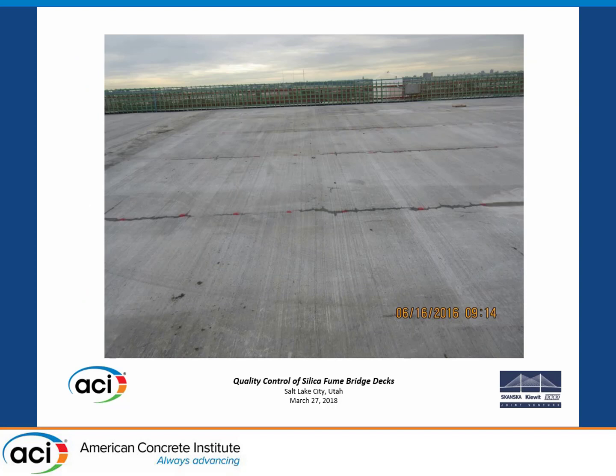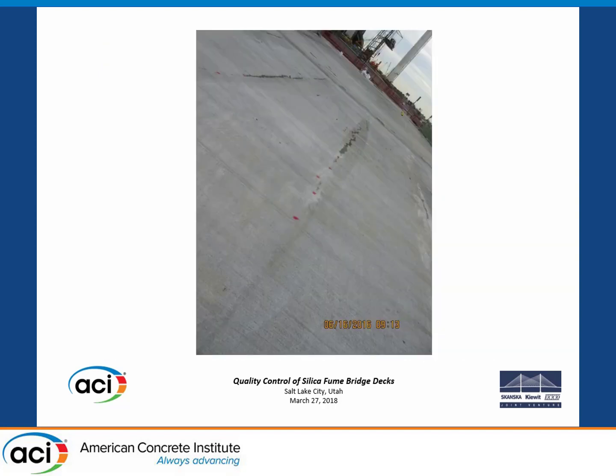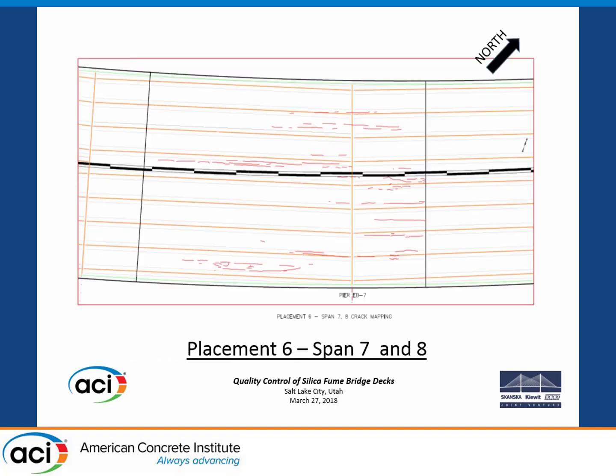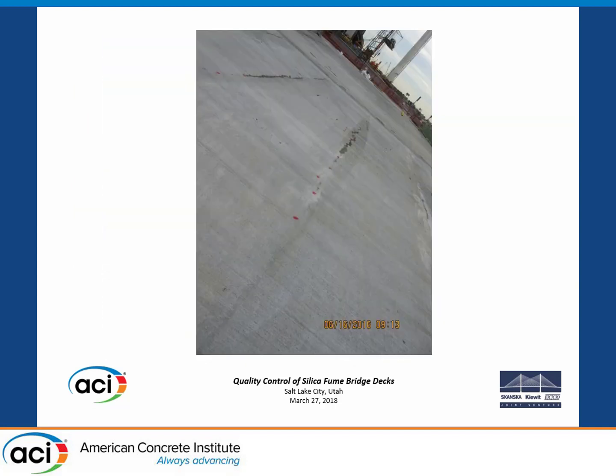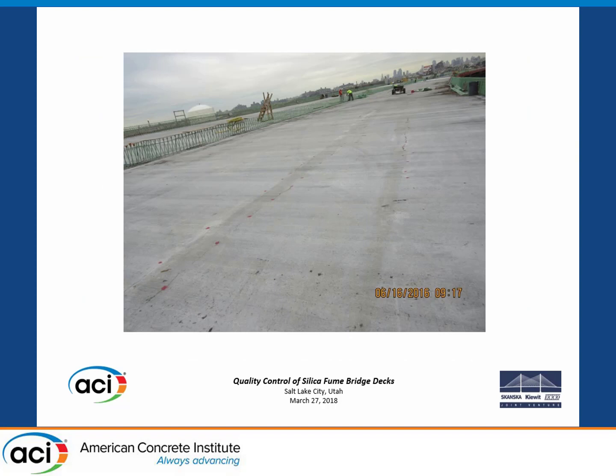And people thought, well, they're over the AASHTO girders. You know, we got negative bending over the AASHTO girders. Something went wrong. But when we mapped them out, we found they were 8 feet apart. That happens to be the width of the covers we used. And there's another shot, 8 feet apart. And if you look at the diagram here, they're not over the AASHTO girders for the most part. They're distributed between, basically 8 feet apart. So my conclusion, and our conclusion, was that they were shrinkage cracks.